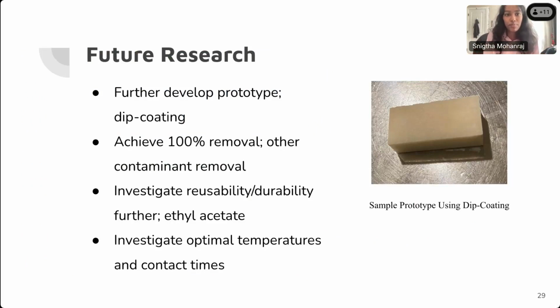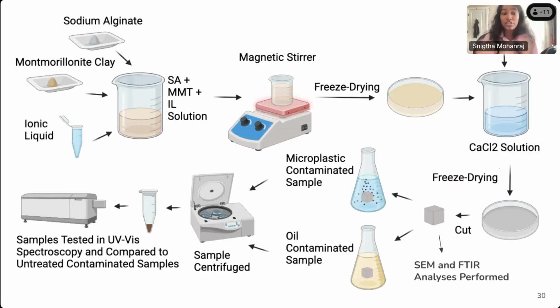And so this is a graphical abstract just to cover what I've done basically in this project, which was mixing the sodium alginate, montmorillonite clay, and ionic liquid in a solution, magnetically stirring that, freeze drying, adding it to a calcium chloride solution, freeze drying it again, and then cutting it, taking that to measure in the SEM and FTIR analyses to look at the composition, but also using those components to treat the microplastic and oil contaminated samples, centrifuging it, and then putting it into the UV-vis spectroscopy to collect data.